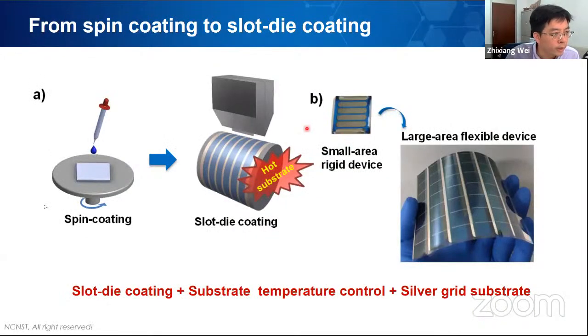In this strategy, we call it synergetic optimization. We change the slot die coating temperature, we control the substrate temperature, and we use the silver grid substrate. Finally, we can extend this strategy from the small area rigid device to the large area flexible device. This is the real image of our device.